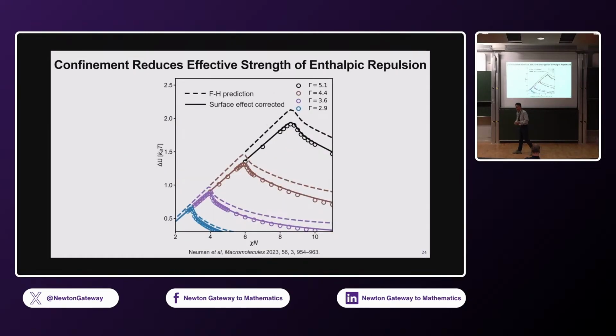So we looked at different factors. Let's first take a look at how the enthalpy of mixing should change. When demixing occurs, the enthalpy should decrease, because AB contacts are replaced with AA or BB contacts. So that's what you see. If we look at what would be expected from the Flory-Huggins prediction, let's just take a look at one example. This gamma, again, is the confinement ratio. As you increase chi N, at some point you're going to see phase separation and enthalpy decreasing. What we see in our simulations is that the enthalpy reduction is actually much smaller.